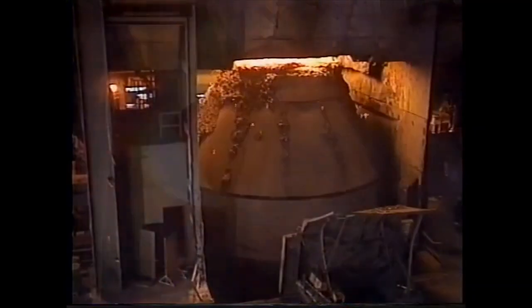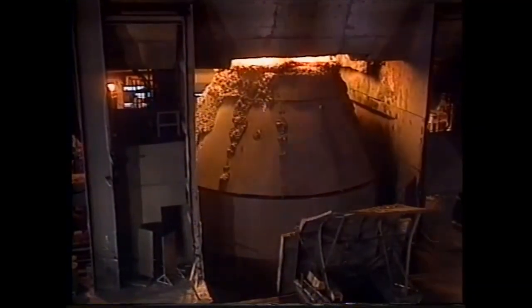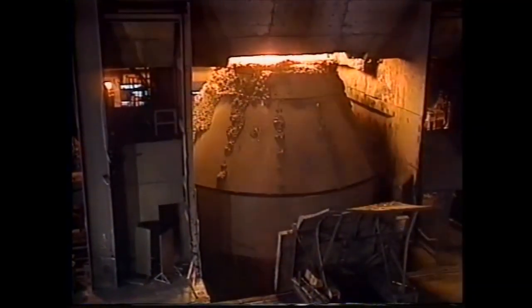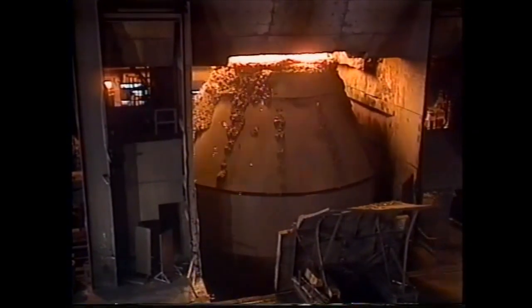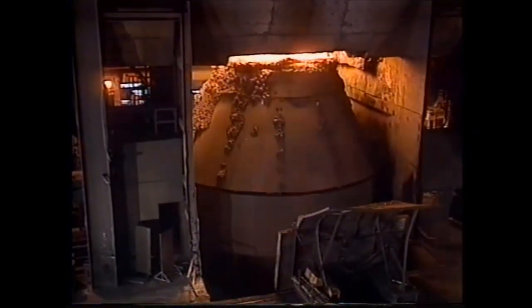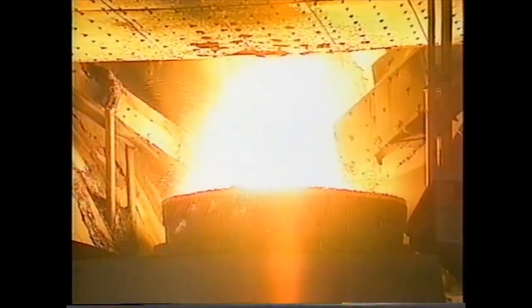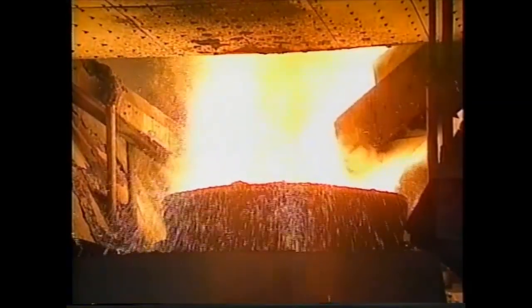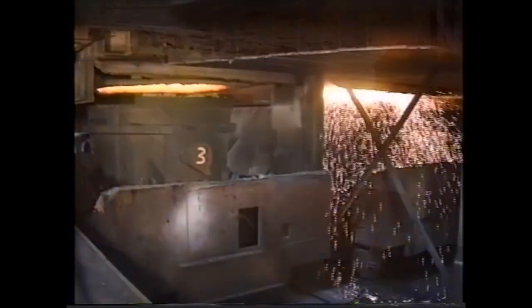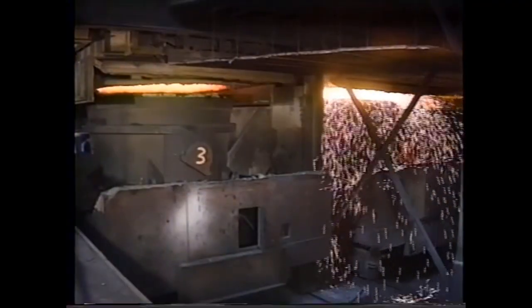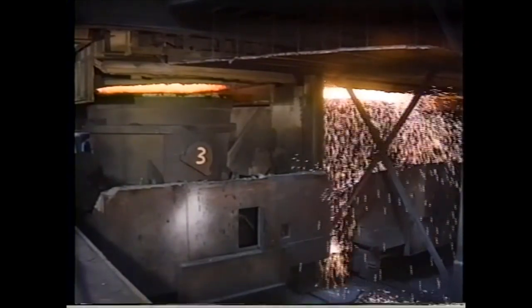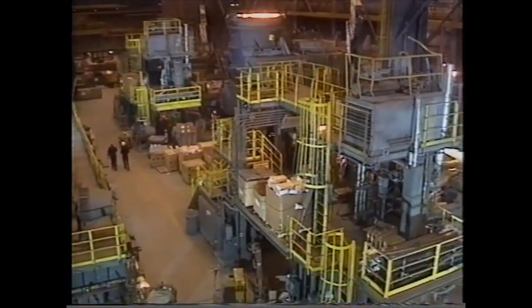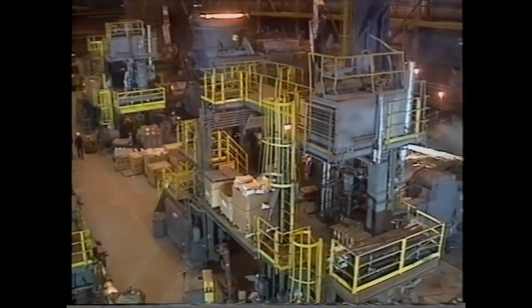Large volumes of oxygen are blown into the vessel at supersonic speed, and the rapid oxidation turns the iron and scrap into steel. After approximately 40 minutes, the steel is poured from the furnace into a ladle. In both the furnace and the ladle, the steel is metallurgically fine-tuned to meet precise chemical specifications. From the BOF, the steel proceeds to the continuous slab caster.